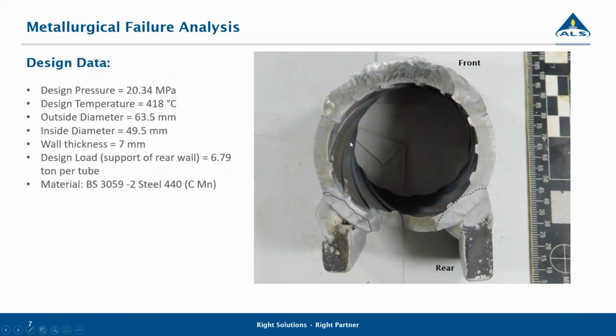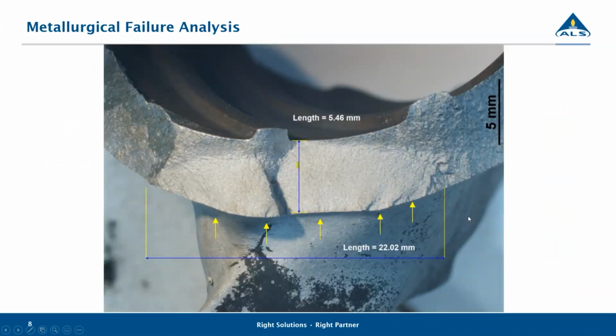You can see here is the failed surface of the tube, just above the two brackets. You'll see this is the first area which cracked from the toe of that bracket into the tube, nearly through wall, and then we also had the other side which didn't grow so deep, but before it leaked, the rest of the section failed, and it's quite a large section that has failed. Here's a little bit closer look at that tube failure. That's the first bracket. So you'll see here that the crack length was about 5.4 and through thickness is 5.5. Now the tube is supposed to be 7 mm, so there was some material loss on this side.